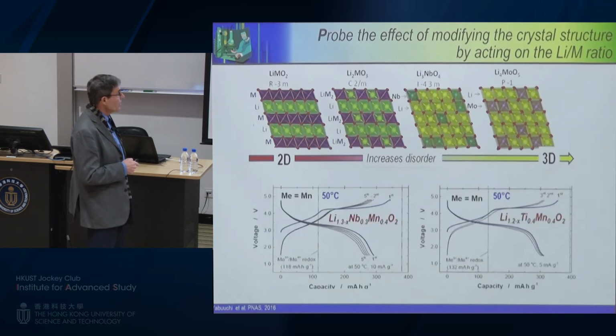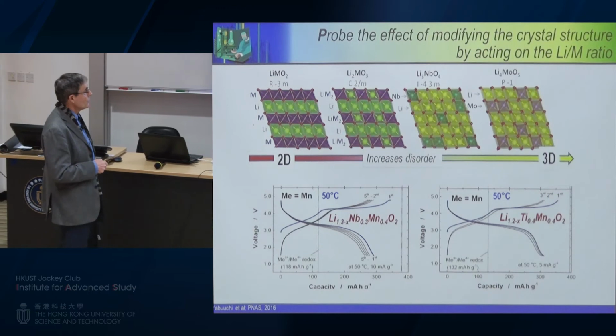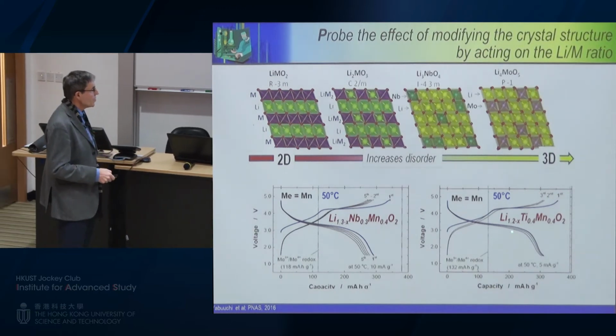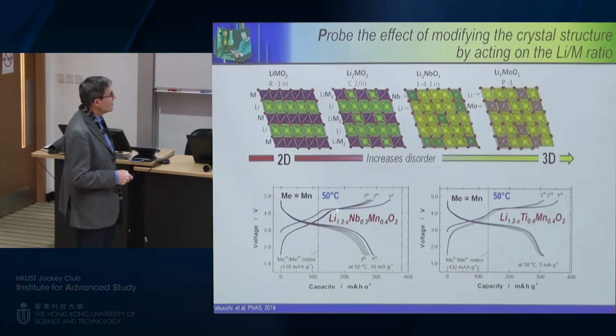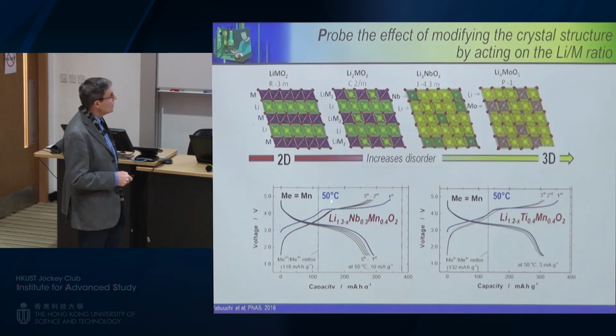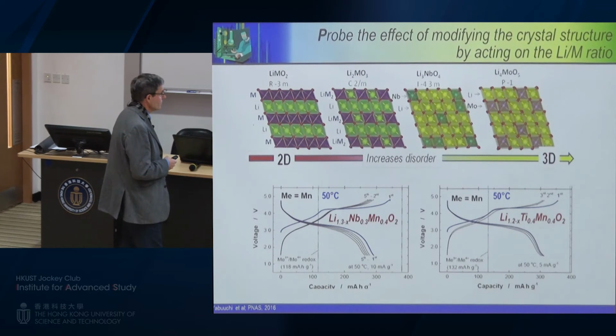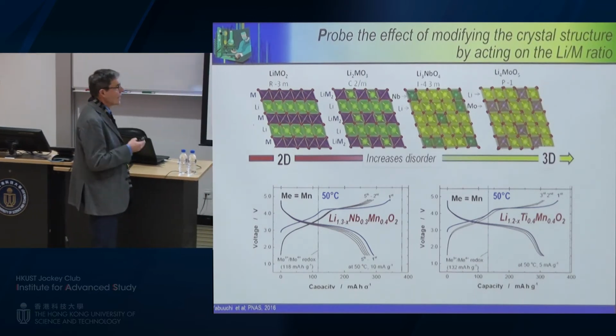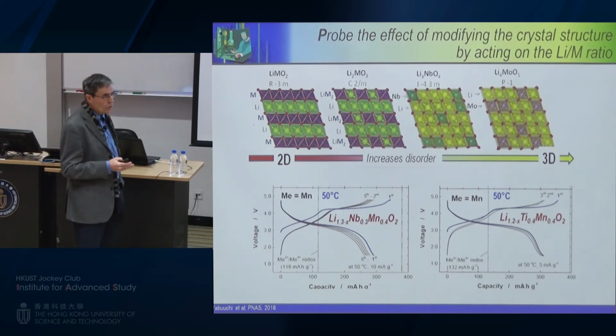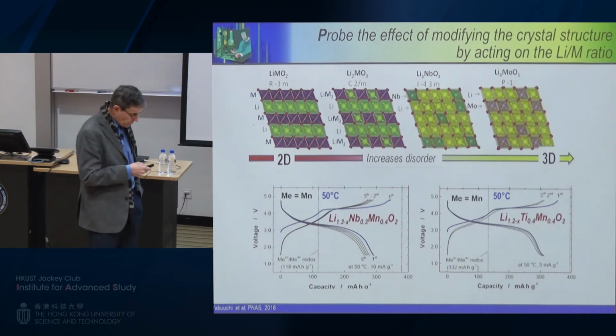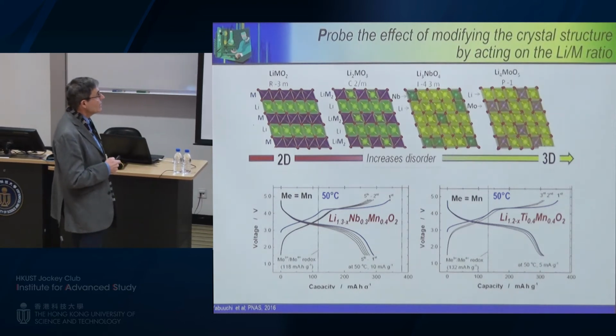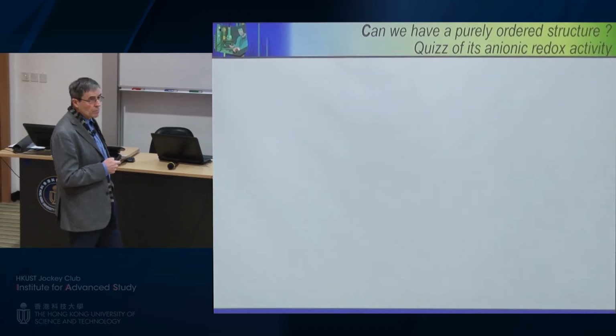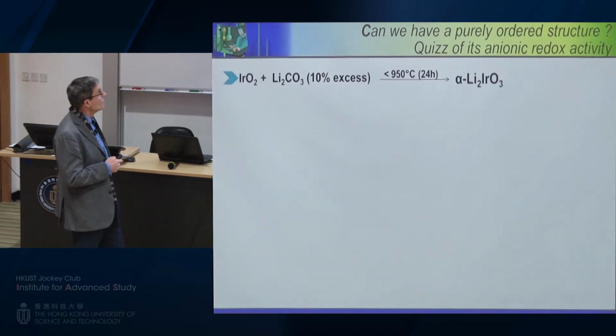And when he was doing this, he was able to get a kind of nice compound, as clearly indicated here, but again, the kinetics was very poor, since he was obliged to go to 950 degrees C to prepare these materials. So the question was, can you make a well-ordered 3D structure? So these are more or less the targets that we tried to achieve, and we succeeded by ideally going back to our classical lithium-iridium compound.